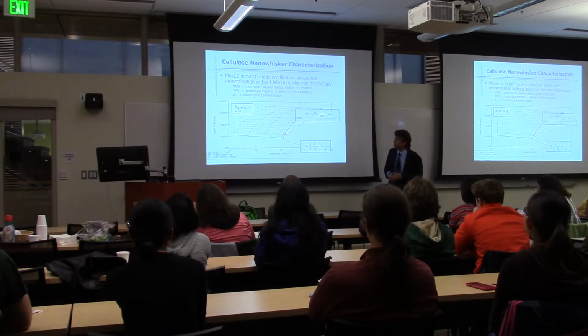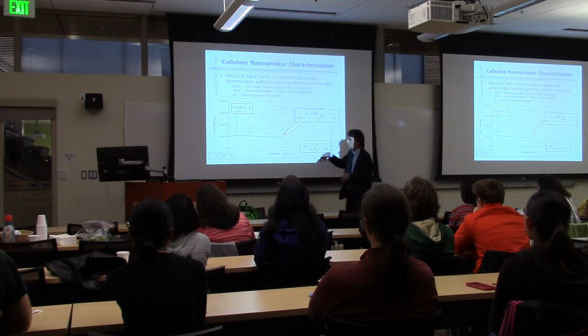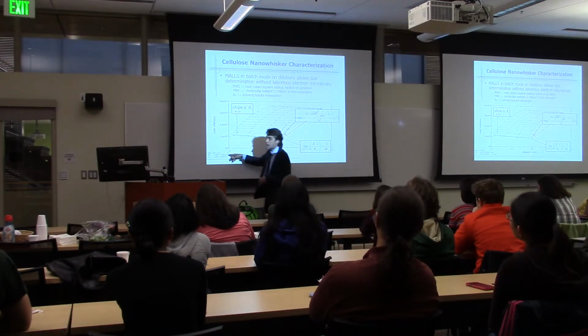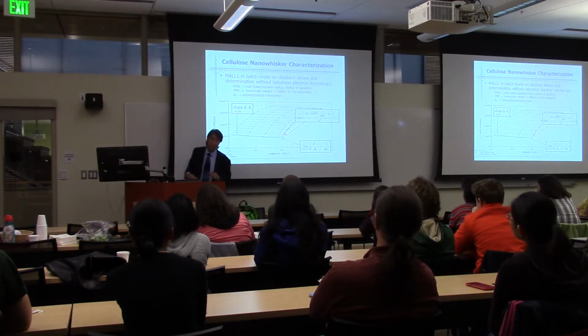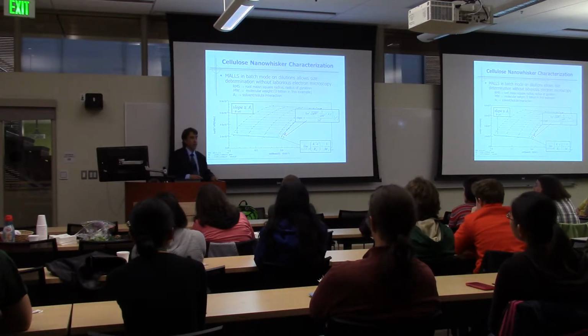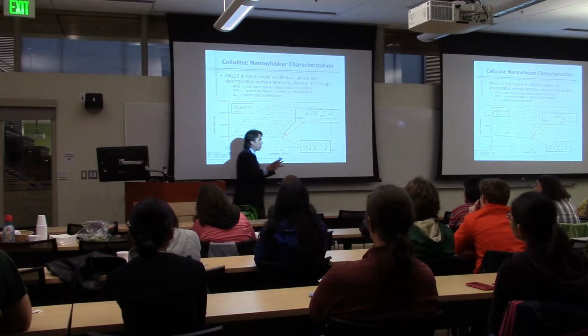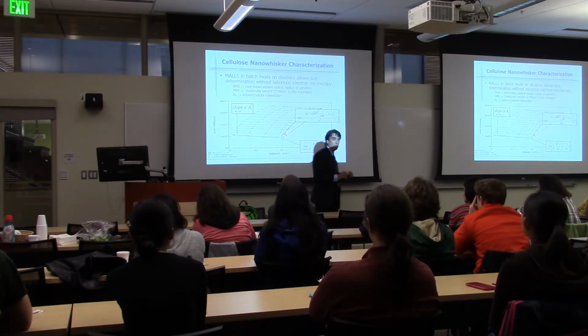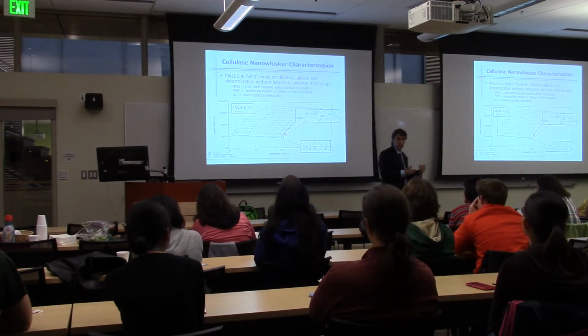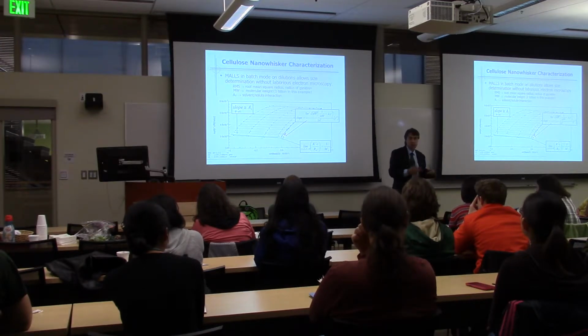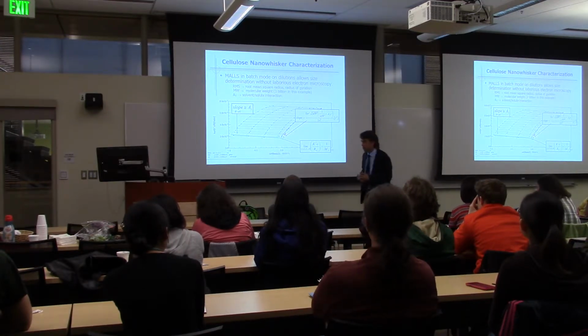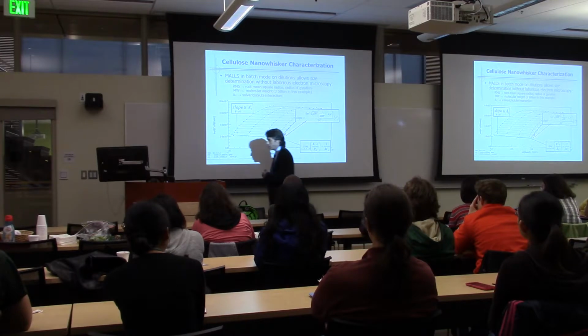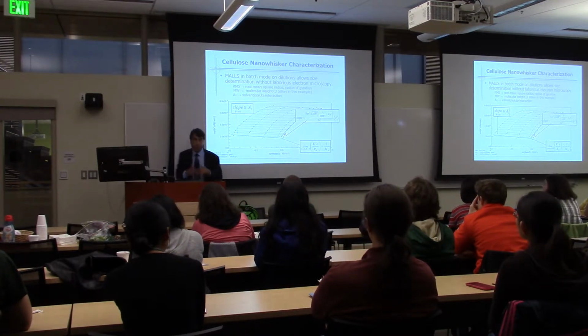And so you probably can't read these numbers, but down here it's telling me that the molar mass that we're measuring is 3 billion grams per mole, okay? 3 billion grams per mole. So again, this is at the nanoscopic level. This is really a supramolecular assembly. The technique is perfectly fine for doing small particles like this. It still holds and still gives you the weight average molecular weight, but it tells you something about the size of the structures that we're dealing with.